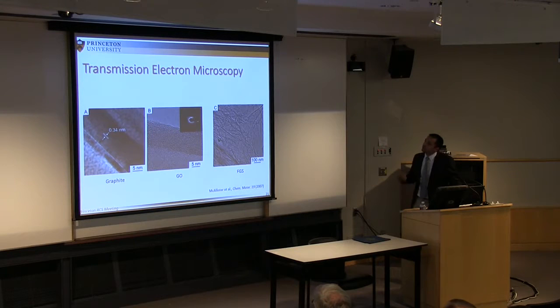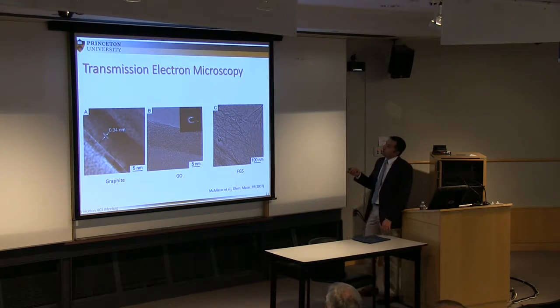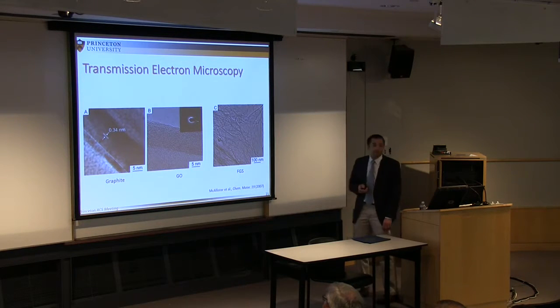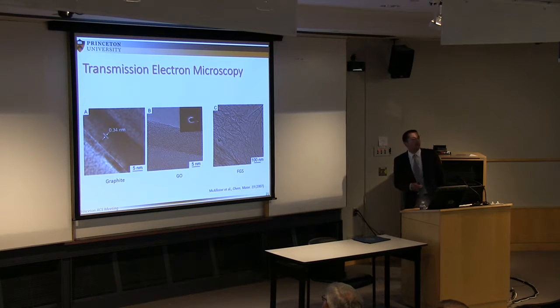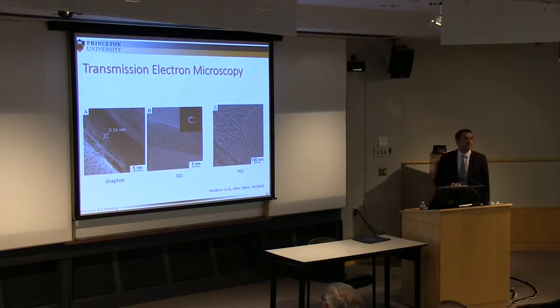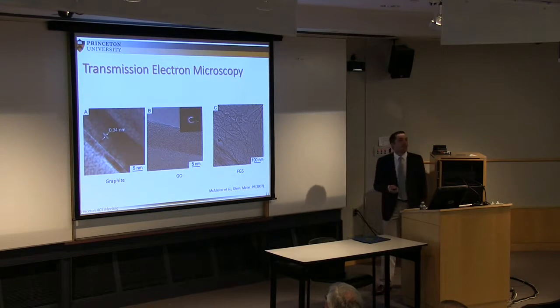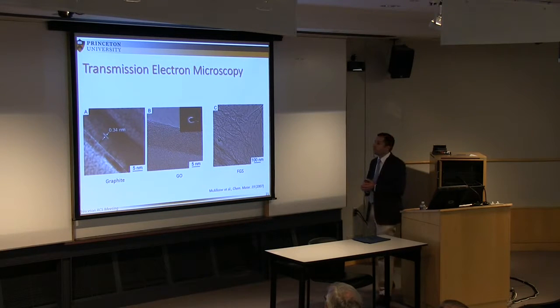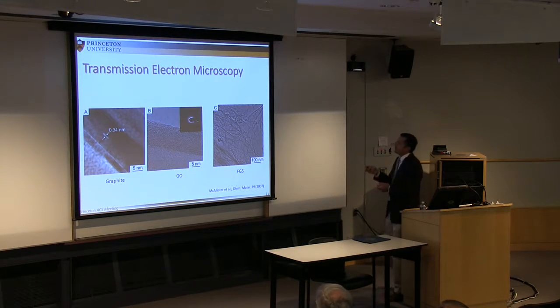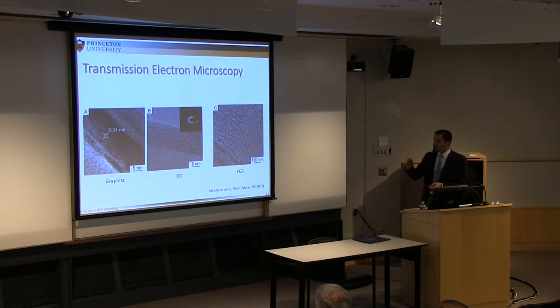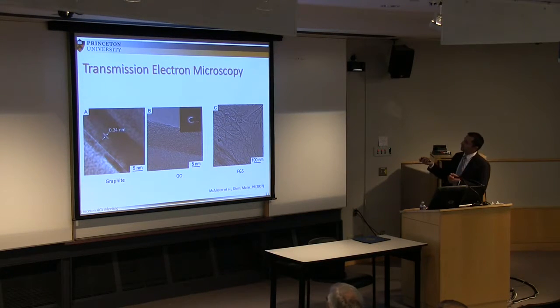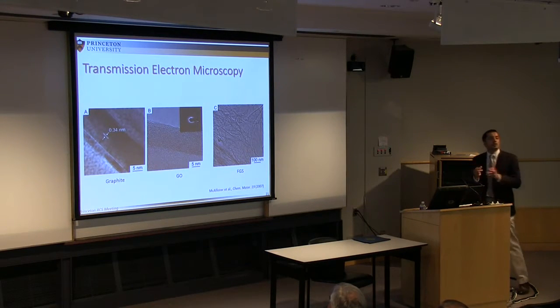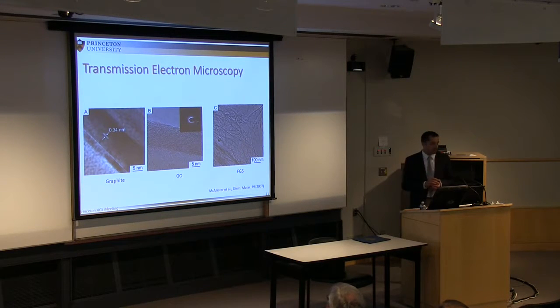Here are some images of the material synthesized here in our lab. So you have, just for your record, graphite here again with the perfectly aligned lamellar structure. This is graphite oxide. You see it's already becoming a mess. So what's happening here? This is simply due to the fact that we have now all these functional groups in between the different planes. So from this material, as I said, if you heat it further under inert atmosphere, you can get what we call functionalized graphene sheets. So those are now individual graphene sheets that are highly functionalized and also have lattice defects.